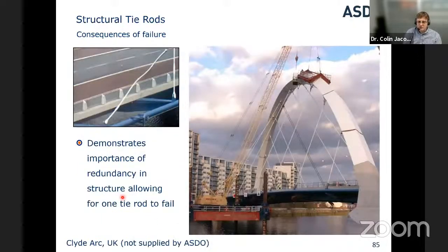But it does also demonstrate on this project the importance of redundancy, because this structure had been designed well. Even though one tie bar failed, it did not lead to a catastrophic collapse, but also it did allow replacement of all the tie rods. So as you can imagine, none of the castings were trusted on this bridge, so every single tie rod was replaced. And that could happen because you could take one tie bar out at a time and just replace it with a new tie rod.